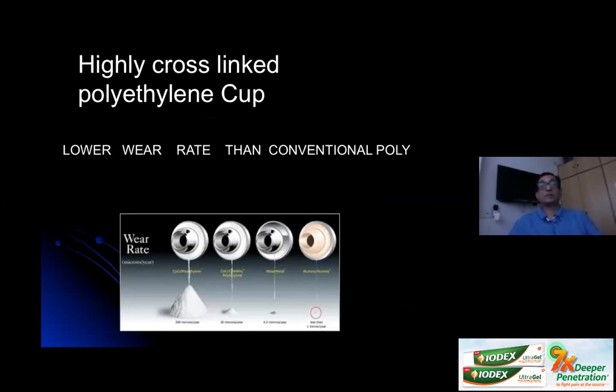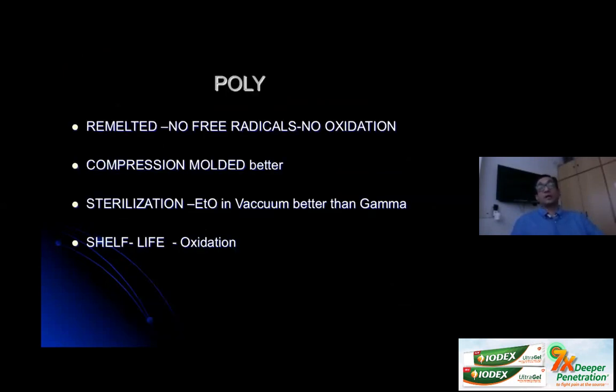And as Dr. Dewnany has already told you, the highly crosslinked polyethylene and highly crosslinked polyethylene on ceramic is today the gold standard in doing a hip, and the wear rates are much lower than the conventional hips, conventional poly, and so this should be what we should be using. Again, when it comes to poly, remelted poly is always better because it has lesser free radicals and there is no oxidation. A compression molded poly during manufacturing is better than machined poly because it has lesser wear.